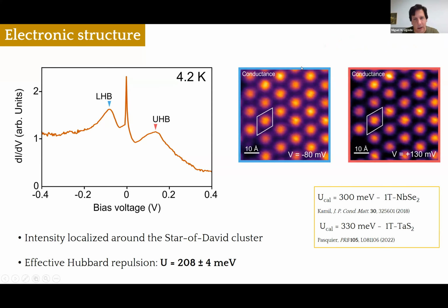First of all, because we have done conductance maps at these energies, right? At 80 millielectron volts, which corresponds to the maxima of this peak, and at 130 millielectron volts, the maxima of this peak. And basically, the conductance map is telling us where the wave function associated to these resonances is located. In this case, unlike in the case of tantalum diselenide on graphene, the maximum of the intensity is located at the center of the Star of David, which is what we expected for the upper Hubbard band and lower